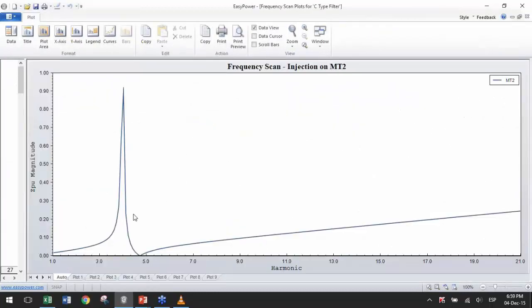Now I get two important points. This spike here is the resonance, which is a point that I want to avoid, completely avoid. And this is the anti-resonance, which is the point that my filter is tuned to. This is a fifth harmonic filter, and the anti-resonance is a little lower to avoid drawing much current, and there are other factors which I will not discuss in this webinar, but this is the anti-resonance.